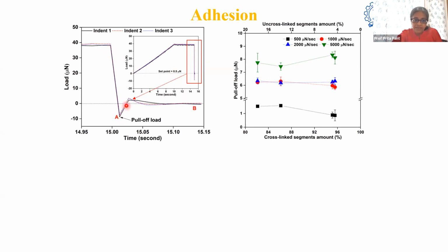And then it tries to bring it back to 0 by pulling it against the adhesion. And this peak is what we measure as adhesion during unloading. So you can see these pull-off loads. They are a function of how fast we are unloading. So I want you to just focus on the fastest unload that we could do, 5,000 micronewton per second. And the pull-off force is about 8 micronewton. It's not huge, but it's there. And it's not varying a whole lot by the amount of cross-linking.